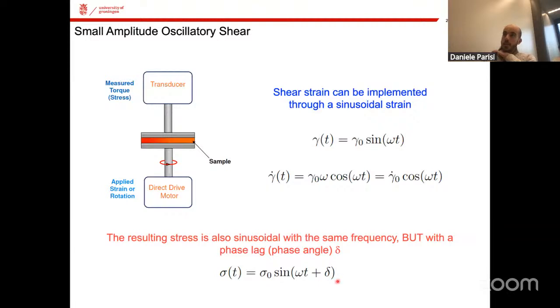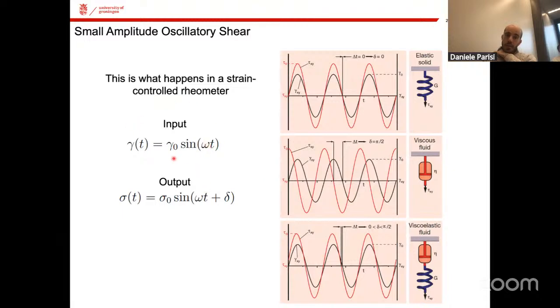And this is basically the nature of the viscoelasticity in polymers, because if I have this input and then I get the stress, sigma, as an output, I know that if this shift is equal to 0, so input and output are in phase, then we are measuring an ideally elastic solid. If this delta is 90 degrees or pi half, so it means that I input a sine and I get a cosine as a response, then it's a pure viscous liquid, like water, for instance. But if this delta is between 0 and 90 degrees, I have a viscoelastic fluid. Of course, if this delta is closer to 0, the elastic contribution is higher, and vice versa. If this delta is closer to 90 degrees, the material is more viscous.